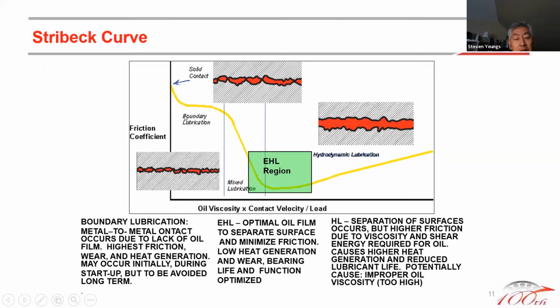When you look at the graph, there are three conditions. Boundary lubrication is on the left-hand side, where the friction is very high. That's the situation when the oil film basically doesn't exist or is very thin, and it cannot protect the bearing surfaces. The reason is either the selection of the oil was not adequate, or the velocity is not there. For applications that run at less than, say, 5 RPM, naturally you are in boundary lubrication conditions, and there's not much you can do except expect the bearing wear to start from the get-go. But as conditions get better, maybe the viscosity becomes higher, a thicker oil film, or the velocity is higher, the oil film becomes thicker.